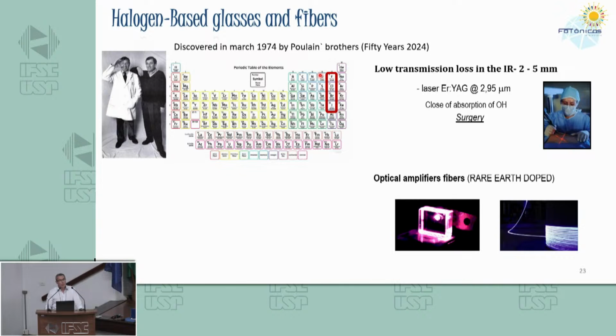These optical fibers present very low transmission loss in the infrared. This is a region where silica glass cannot be used, because silica glass can be used only up to 2 or 3 microns. If you need to go further into the infrared, you need, for example, fluoride fibers. The best-known fluoride fiber, ZBLAN, is a zirconium-based fluoride fiber that can achieve 7 microns in transmittance. Some fluoroindate glass can achieve up to 10 microns.